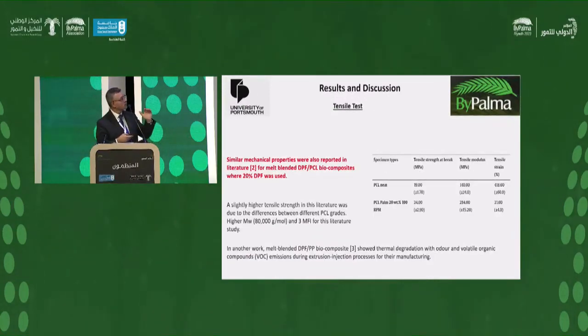And then similar mechanical properties were reported in literature too. So slightly higher tensile strength in their literature, and then the modulus increased, but perhaps because of the grade of PCL used, we had slightly different results obtained. Another work they have, in reference 3, I'll show that reference in the end, covers thermal degradation and some other properties produced by extruder.